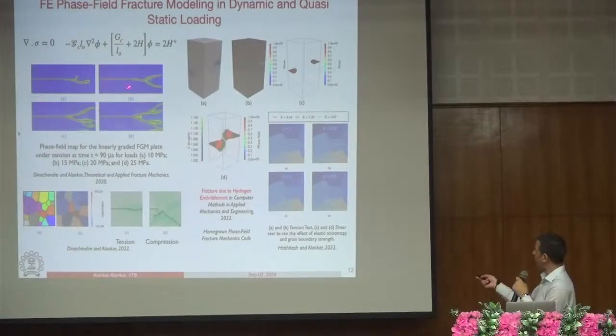This is elastodynamics, where we introduce a straight crack and introduce a pulse here, right? Shock pulse, and we are trying to analyze if the material is gradient vertically or horizontally, or how the crack fragmentation changes because of the pulse. If the pulse is stronger, the crack will fragment more. If the pulse is weaker, crack will fragment less. And it talks a lot about how the fracture toughness is changing as a function of pulse.